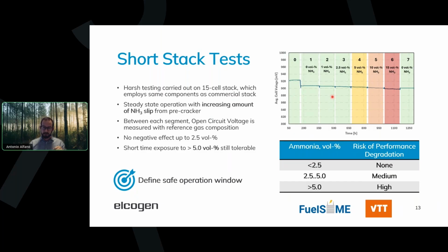the layers. You can probably see that for up to 2.5 volume percent of ammonia, the voltage was not substantially changing. We still see a decrease. That's because the endothermic reaction of cracking ammonia is decreasing the voltage because of the temperature decrease. So this is coherent with the results. But then when you go to very high ammonia content, you start to see that the voltage stability is starting to look less stable in that sense.